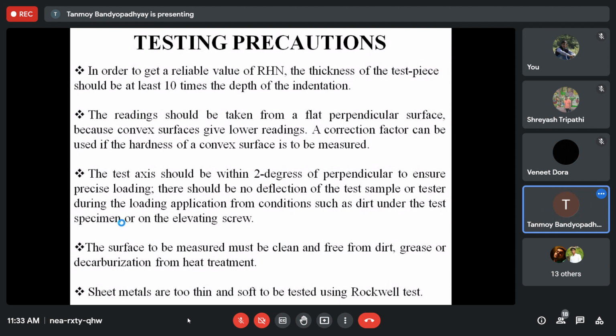Whenever you are indenting a surface, if the specimen itself is not rigid enough, like a very thin specimen, then when you apply the load using the indenter, the specimen will start to bend, so the measurements won't be accurate or reliable. That is why the thickness of the test piece should be at least 10 times the depth of indentation. So the depth of indentation should be 1/10 of the thickness. You cannot indent it up to, say, 50% of the thickness.